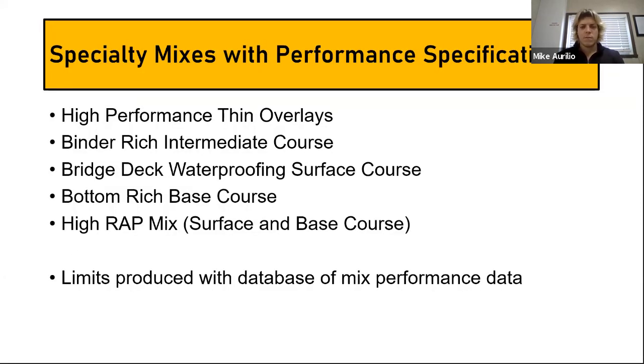So speaking about those specialty mixes, there's 5 that are included in this report. You've got your high performance thin overlays, your binder rich intermediate course, bridge deck waterproofing surface course, bottom rich base course, and the high RAP mix. And these mixes were all developed around the database they developed of performance criteria. So for several years they collected a large number of test results from various mixes, correlated that with field performance, and then found a way to select specification limits based on that data. So they used all that information to help develop these specialty mixes where performance was the priority.